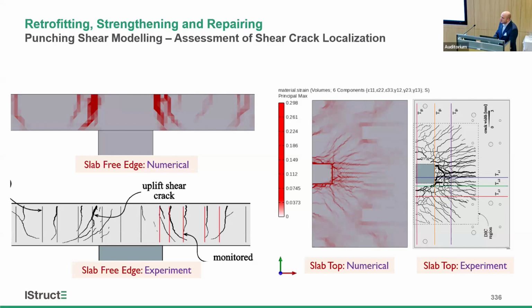Also, the shear cracks are limited by values based on test data. For a slab without links, this is normally between about 0.3 and 0.4 millimeters, and for a slab with links, it's between about 0.6 to 0.8 millimeters or something like that. This is all based on physical test data that's formed the basis of critical shear crack theory, but the nonlinear analysis can model these cracks and how much they're opening up to make a judgment, normally done conservatively, about what the ultimate shear capacity is, and identify the point that precedes the punching shear failure.